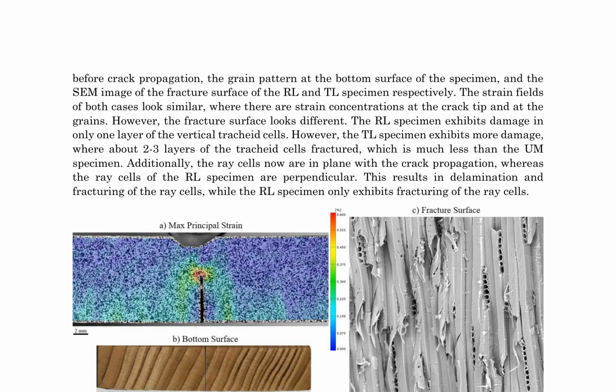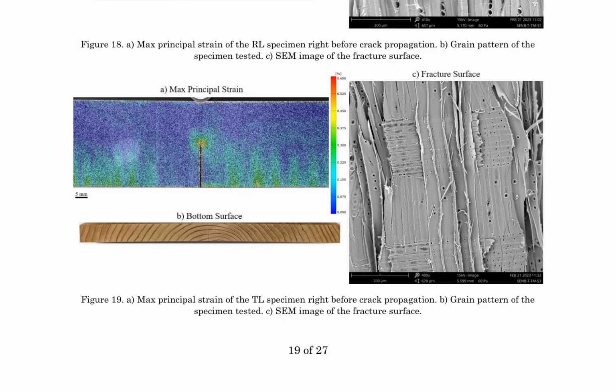The RL specimen displayed damage confined to a single layer of vertical tracheid cells, whereas the TL specimen exhibited more extensive damage across 2 to 3 layers of tracheid cells. Notably, the ray cells in the TL specimen were oriented in the plane of crack propagation, leading to delamination and fracturing of these cells. In contrast, the ray cells in the RL specimen were perpendicular to the crack propagation, resulting in only fracturing of the ray cells without delamination.